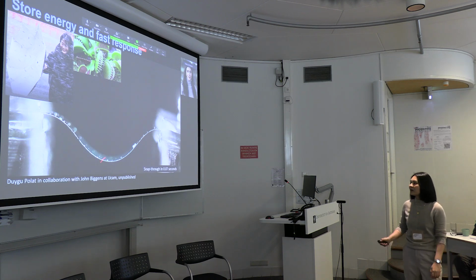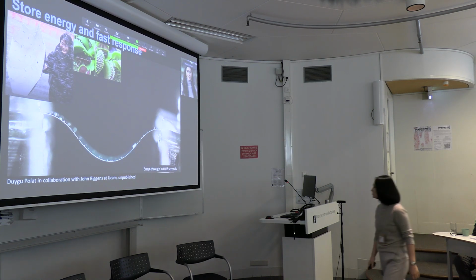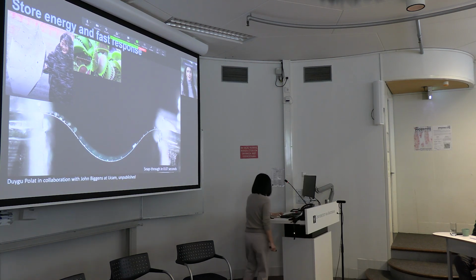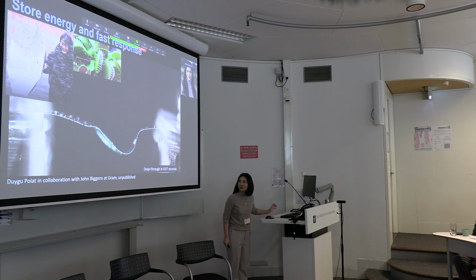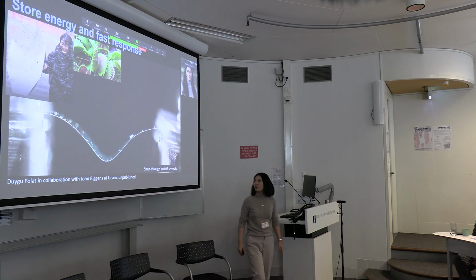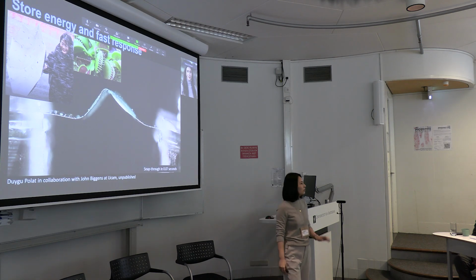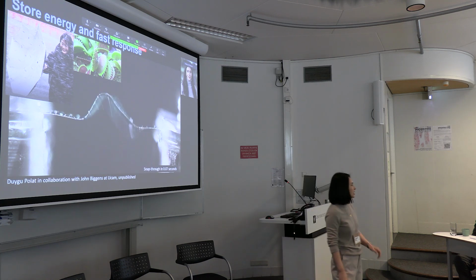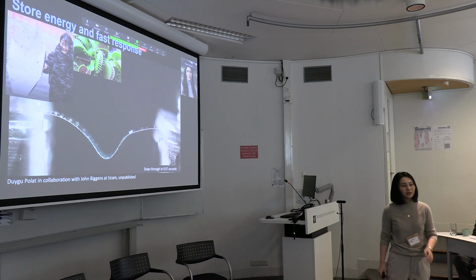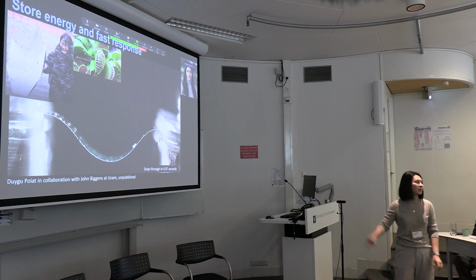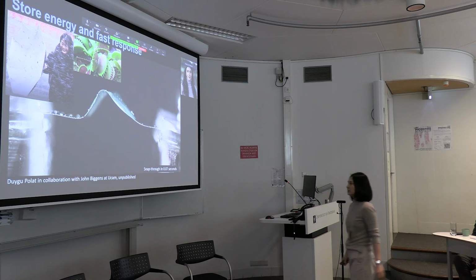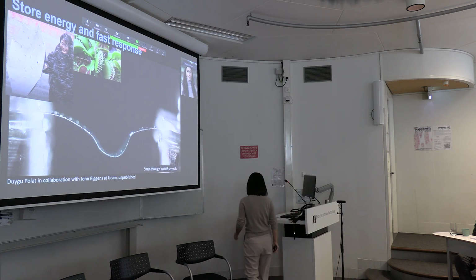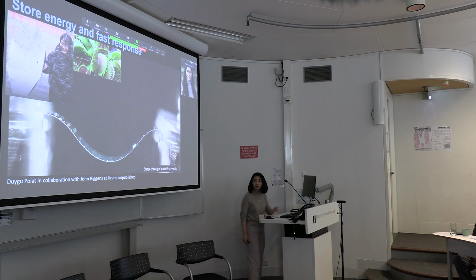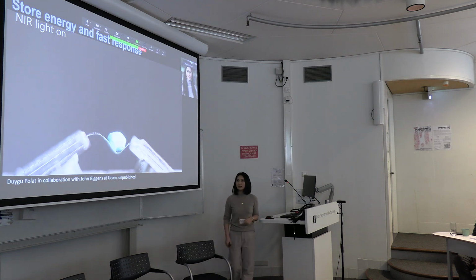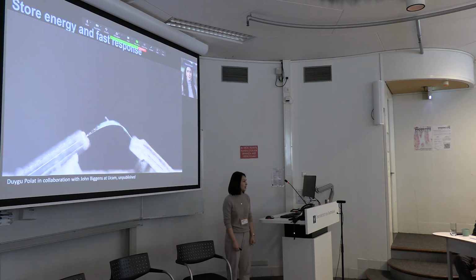Inspired by this, we also started making snap-through systems. So this is the initial state. Then when it gets enough energy, it pops up. Quite often the videos we show are accelerated 5 times or so, but in this case we slowed down the video because this happened in 70 milliseconds. You can see that it's a fast snap-through deformation, and we further use the force generated by the snap-through to throw a ball.